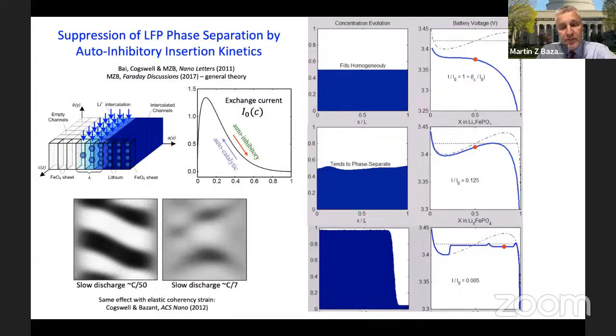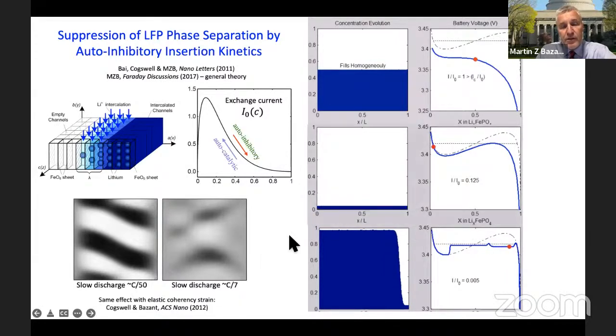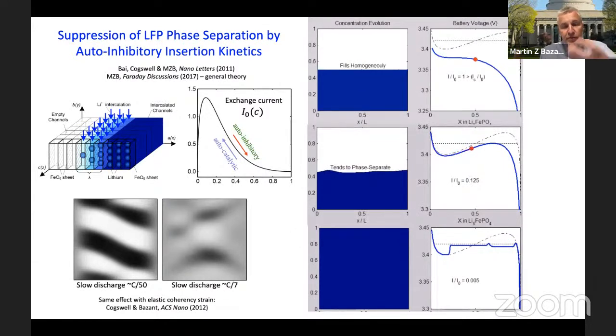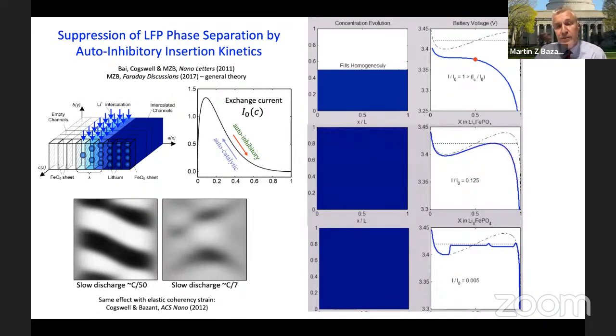But if you simulate the same system at a higher rate, shown here, then you kind of blow right through the spinodal point. You start to see an instability, but then it goes away, and phase separation is actually not achieved in that example.